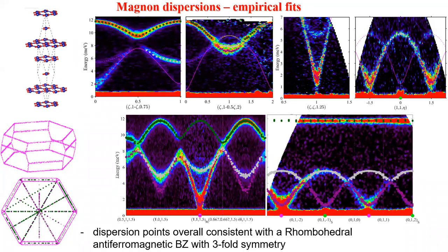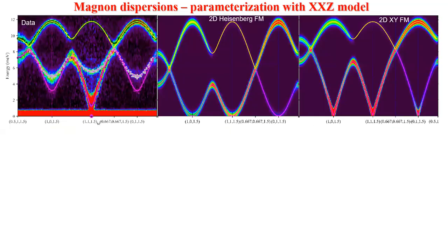So more now about how we extract the magnon dispersion. From the four-dimensional data, we extract dispersion along several equivalent directions in different Brillouin zones, and then we map back to the antiferromagnetic zone, and we see very good consistency over many dispersion points that we extract.